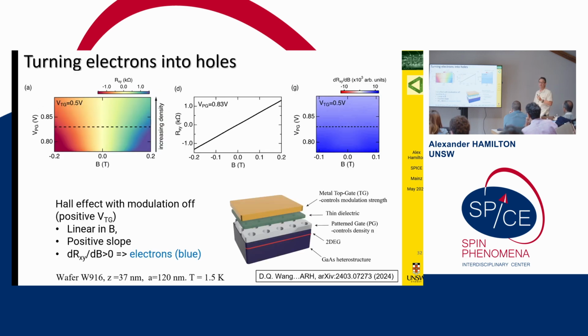So the first thing I'd like to show you is that we can turn electrons into holes. So let me take my 2-dimensional electron system and start with no modulation at all. Then the Hall voltage as a function of magnetic field is a straight line. Okay, we all know this. And the slope of that straight line tells me the carrier density and the carrier type. So that slope is electrons. And if I take the derivative of that slope and plot it as a color, it's positive. So everywhere here, for all of these gate voltages and all of these magnetic fields, this is behaving like electrons. That's no surprise.